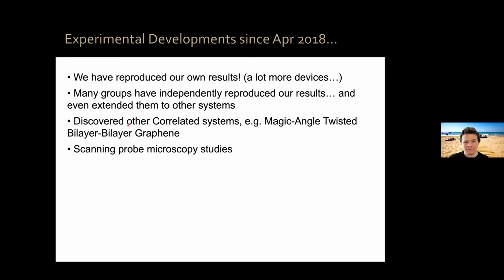Now, we have discovered other correlated systems, for example, magic angle twisted double bilayer graphene, the second twistronic system to be discovered. You take two layers of graphene with the usual stacking that you have in graphite, called Bernal stacking, so zero degrees between the two layers. You have another two layers, again with zero degrees. And now you twist them pairwise. So you have four layers in total, and you twist the upper two with respect to the bottom two by the magic angle. It's not a superconducting system, but it's an interesting correlated system with interesting magnetic properties. And that was the second system to be discovered.